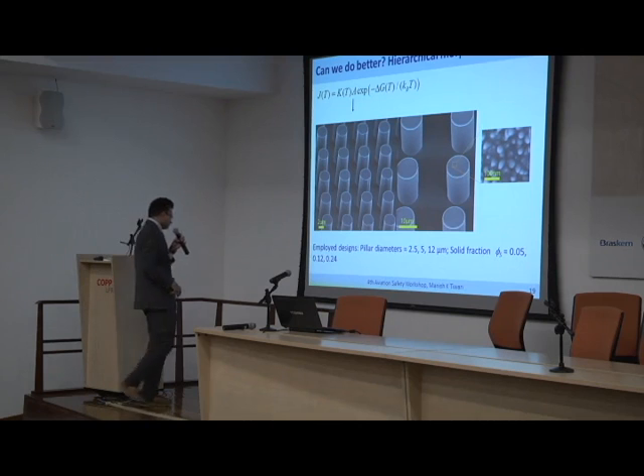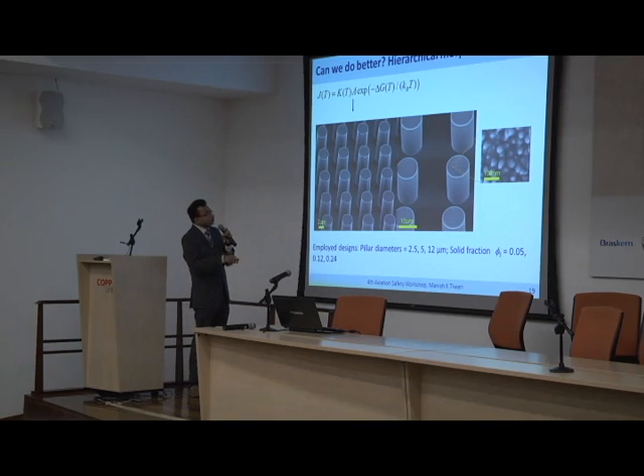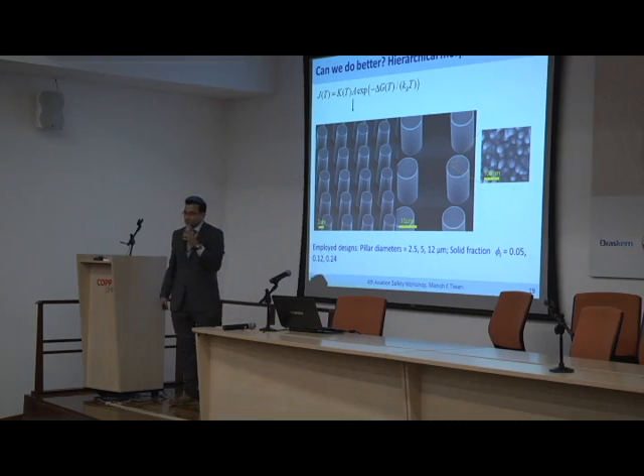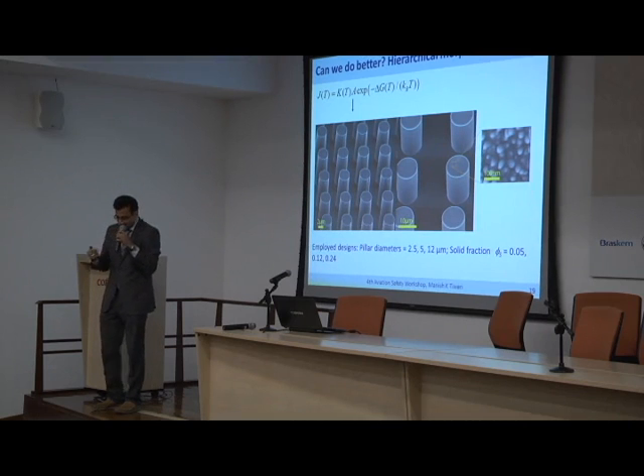And that's exactly what we do. So what we do is we make our surface out of so-called micropillars, and on top of these micropillars, we build in some amount of the nanotexture that we saw before, to get the dual benefit: the nanostructure benefit that we saw, and minimizing the surface contact. Does it work?